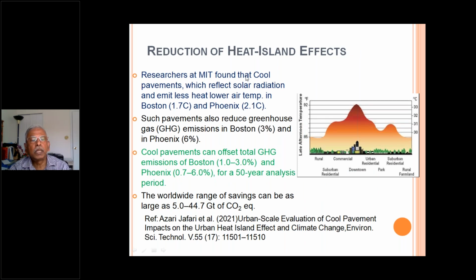Researchers at MIT found that cool pavements, which reflect solar radiation and emit less heat, lower air temperature in Boston by up to 1.7 degrees centigrade, and in Phoenix by 2.1 degrees centigrade. Such pavements also reduce greenhouse gas emissions in Boston by up to 3% and in Phoenix by 6%. This is called the heat island effect. In rural areas, if the temperature is 85, in midtown or the center of the city, it can reach up to 92 degrees.